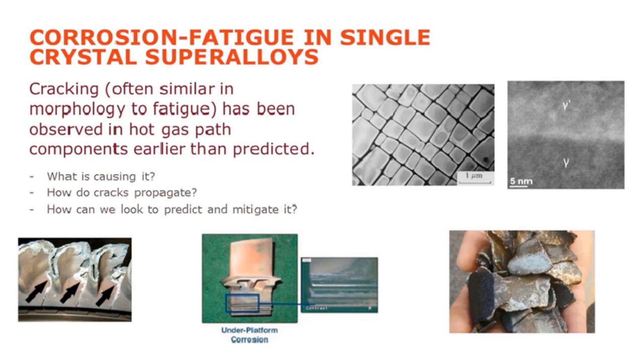in these materials. Certainly at this temperature, obviously things change a bit with different temperatures, but we don't really have a grain boundary, hence why we call it a single crystal superalloy. And that comes with numerous advantages for high temperature material properties, creep, fatigue, things like that. Along the bottom, I've got some images of what typical corrosion fatigue damage looks like. So what we're talking about in this presentation, the types of damage we would see.